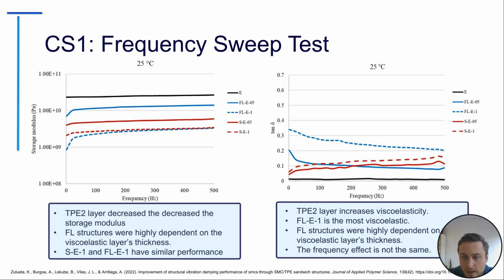When they looked at the damping, they saw that the viscoelastic layer increased the viscoelasticity of the structure, and that the free layer with a 1 millimeter thick core was the most viscoelastic, and that the free layer structures were highly dependent again on the viscoelastic layer's thickness, similar to the modulus.